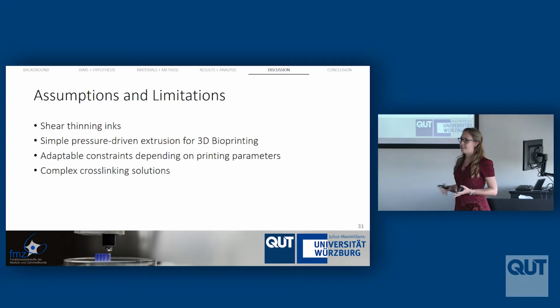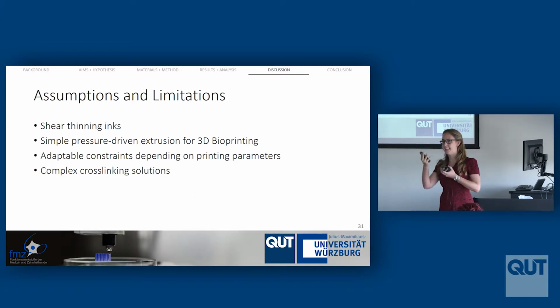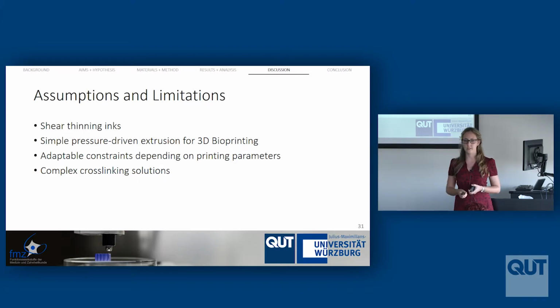So we always have to get to the end of our study and see, have we done something that's reasonable, especially in applying a mathematical model to a physical situation. And of course, I only looked at shear thinning inks, and so these are inks with the very specific properties that get more liquid as you apply force to them. I've used a very simple pressure-driven extrusion model for 3D bioprinting. There are, of course, far more complex bioprinters that apply cross-linking as they're being extruded. There are ones that have multiple axes of needles, so you're printing materials inside of materials that could protect them. I was just looking at simple pressure-driven extrusion of biomaterials, which is a very, very popular technique because of its ease. But we need to know that that could be a limitation of our techniques as well.